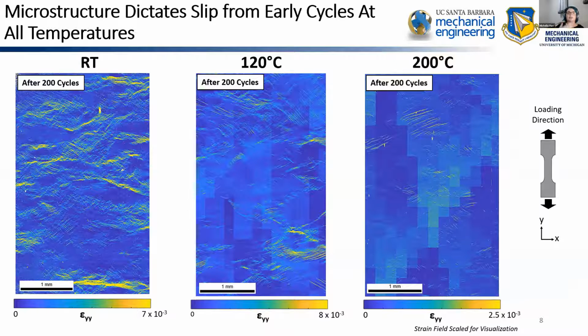So we have a greater rate of accumulation of slip and strain, as well as just more strain overall. The other thing that we can clearly see as we continue to cycle through at every single temperature is that it clearly is related to the microstructure, in that regions that have little to no strain after two cycles continue to have little to no strain with additional cycling, but the regions that have already slipped continue to slip and continue to accumulate more and more slip activity. Again, indicating that this is a microstructurally driven process.